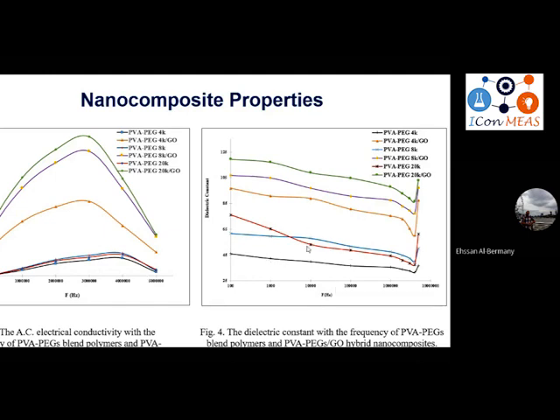We can see both figures. The blended polymers have good properties, but it is improved when we increase the molecular weight, basically in both the AC and the dielectric. Also, the graphene oxide improves both properties: the AC increases and the dielectric constant also. So the molecular weight has a significant effect as well as the graphene oxide.